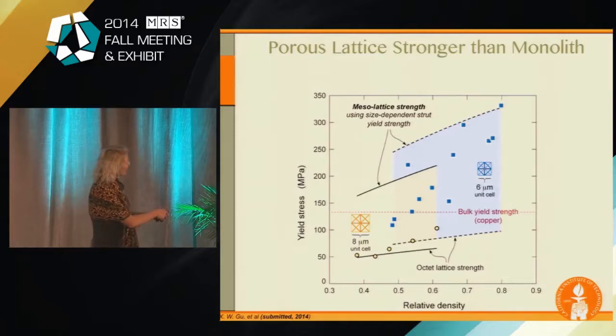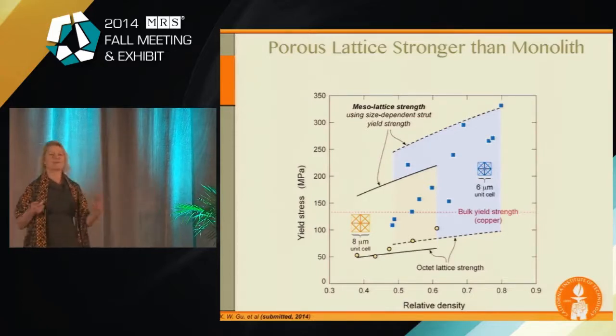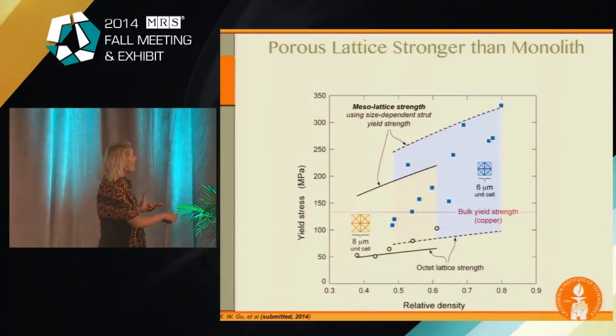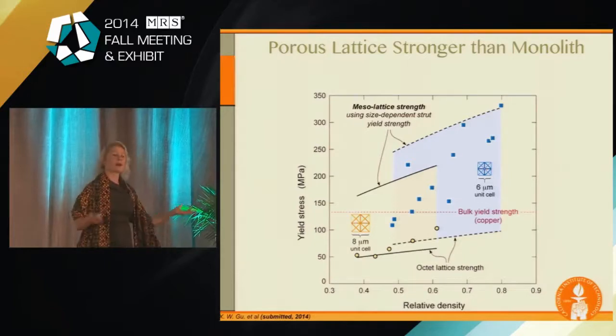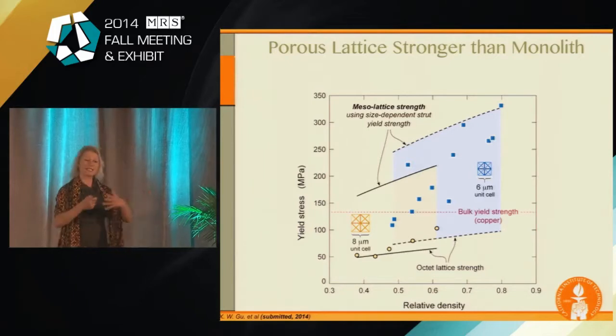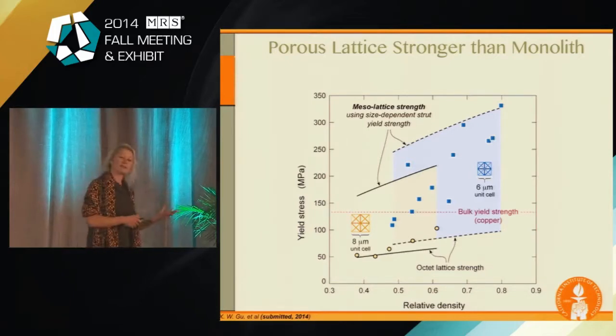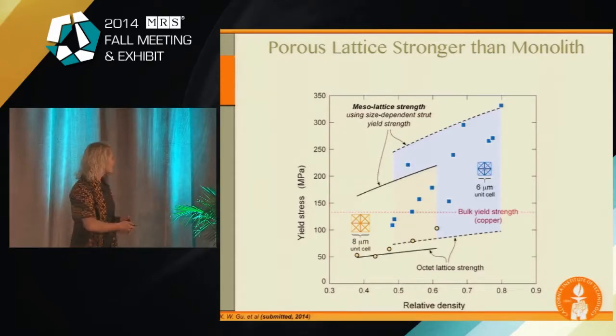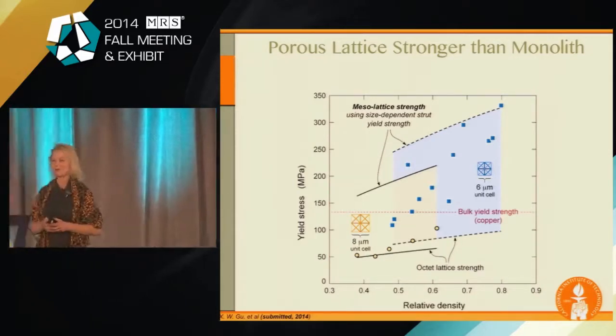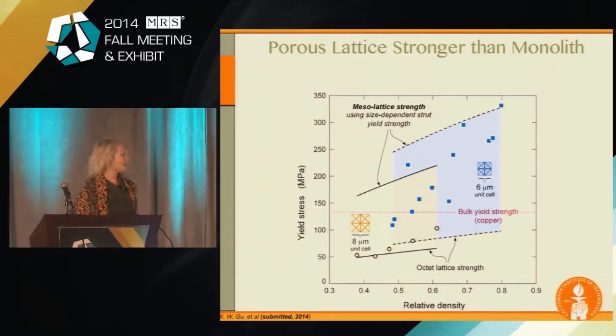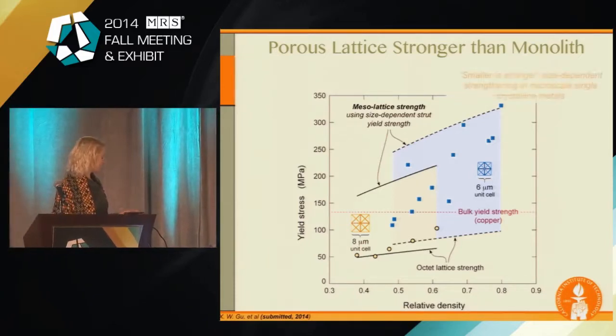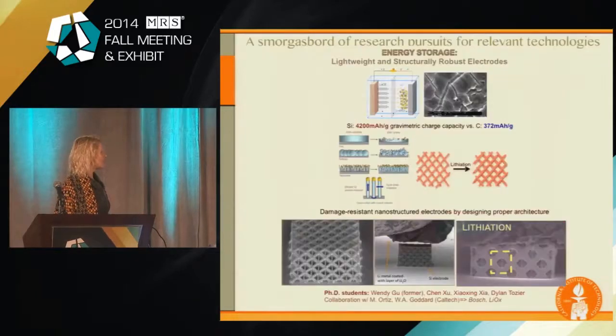And then at these very high densities of about 80%, we can look at it as a composite, an air-metal composite, so we can look at the rule of mixtures and maybe capture it pretty well too. But all of this stuff over here, there are no models that can explain this. All of this is the manifestation of this combined size effect and architecture, and there are no models that describe its behavior. So this is a great playground for our mechanician type colleagues. So we thought this was a pretty neat effect. This is the tenet, the smaller, stronger size dependence manifests itself here, even in these relatively complex structures.